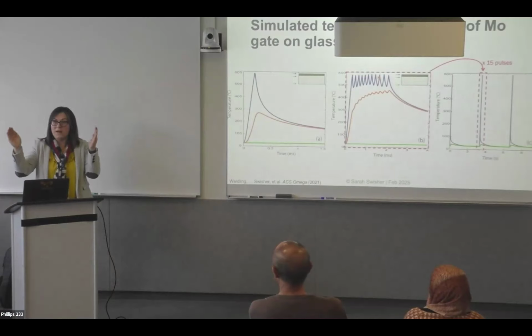So this is an example of a typical pulsing profile that we would use, where we control the on-off times of the lamp, and that gives us a dwell time for our heating. And this individual pulse then can be repeated multiple times. So we would do this 15 times, say. And when we did this,